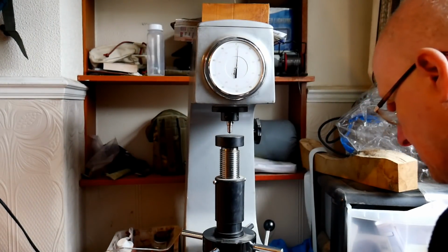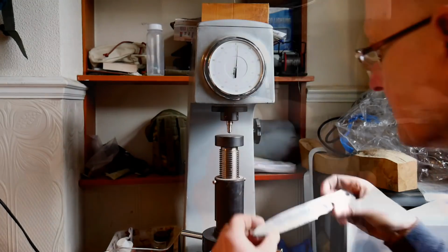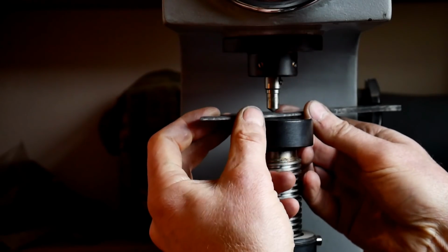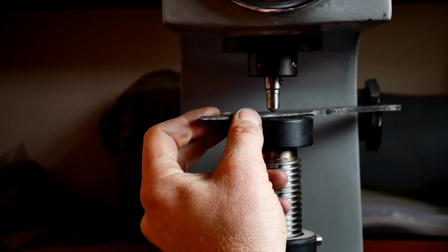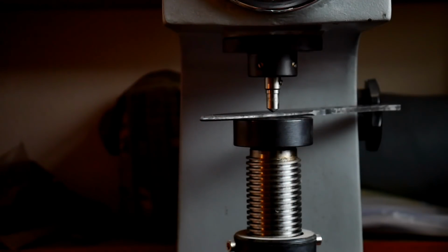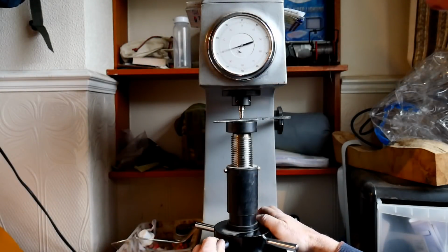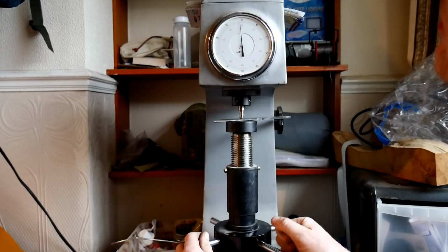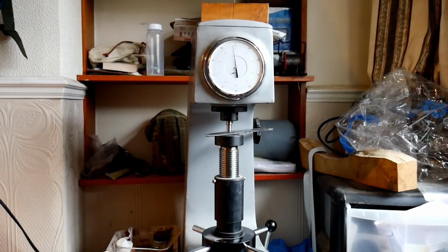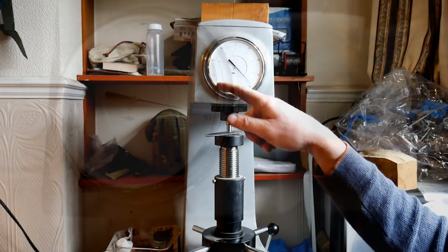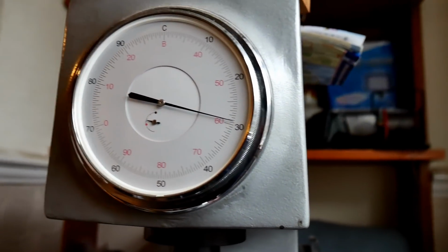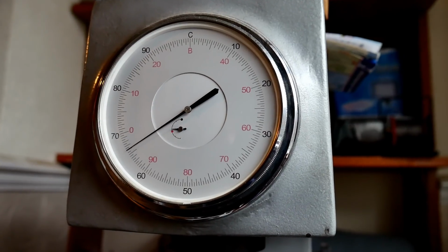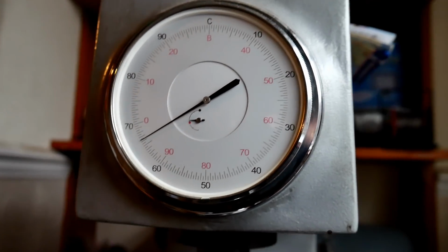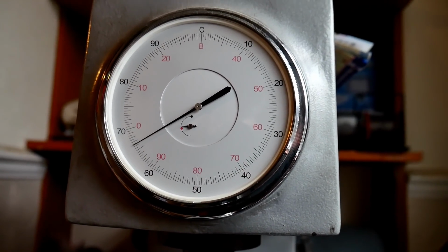Here we are at the Rockwell tester. We're going to test now for that as-quenched hardness. So I load the knife onto the anvil, apply the preload, and we're looking for 65 or higher on the Rockwell C scale, which is the outer scale. Let's see where we're at. So as you can see, we're well over 65 HRC.